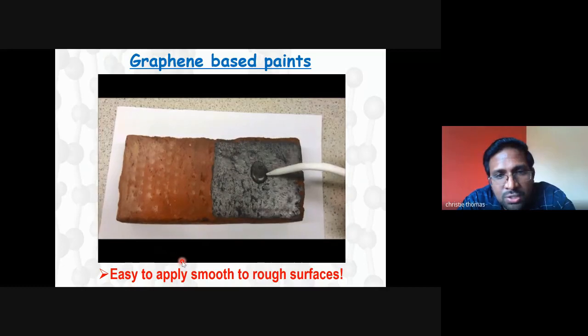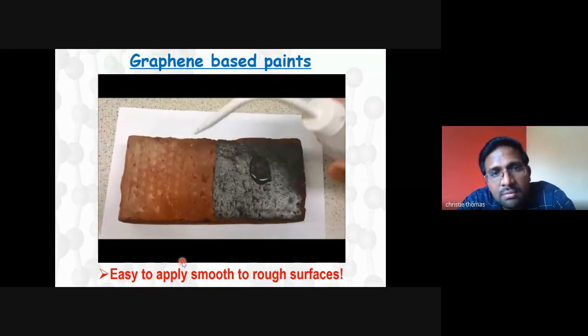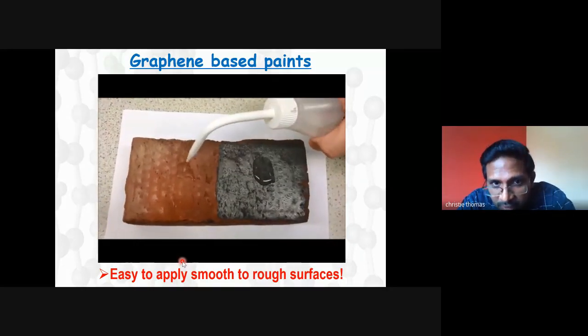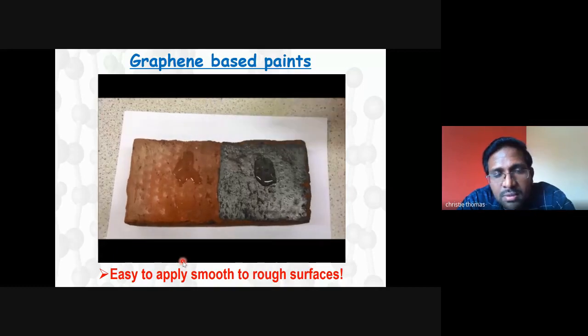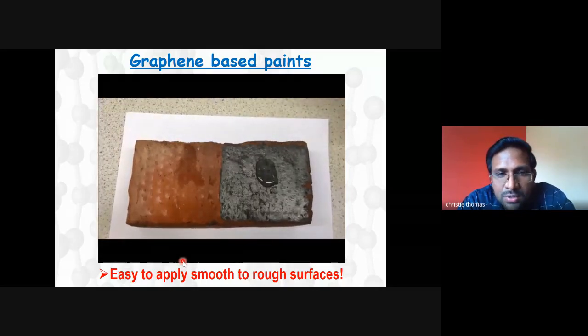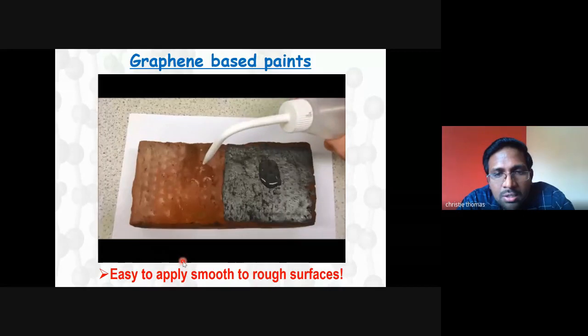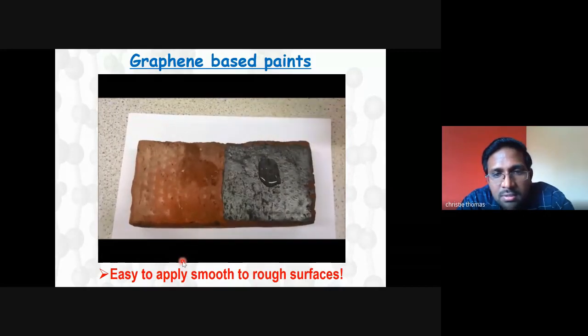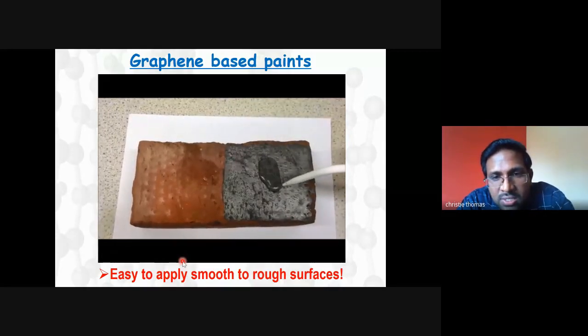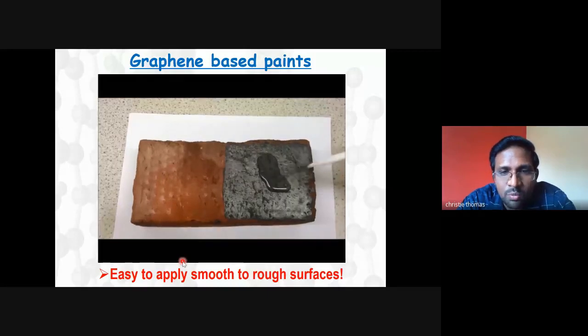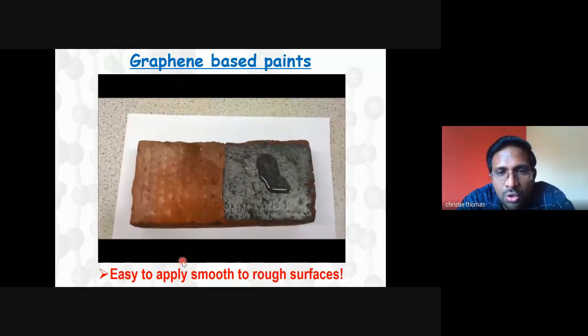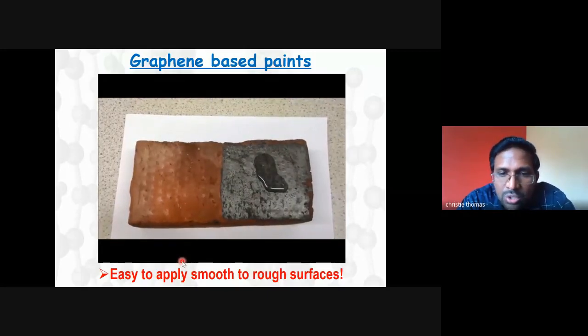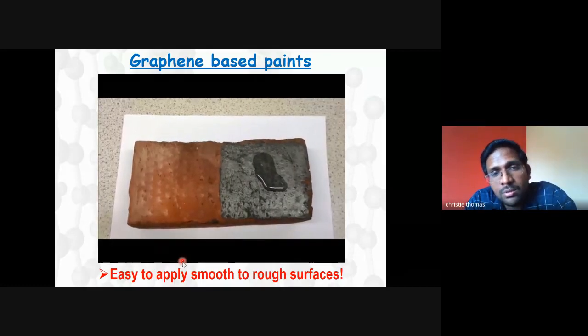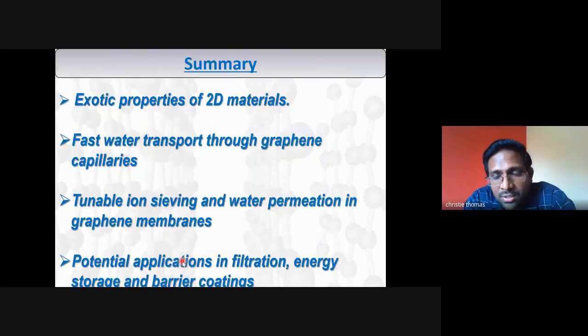One part of this brick is coated with graphene. This is not graphene oxide, this is reduced graphene. That means graphene paint. You can see that on the coated part, water stays there, whereas in the uncoated part, water goes into the brick. So there are a lot of applications for this kind of graphene oxide or 2D material based applications.